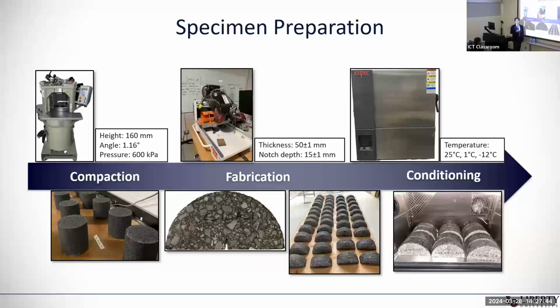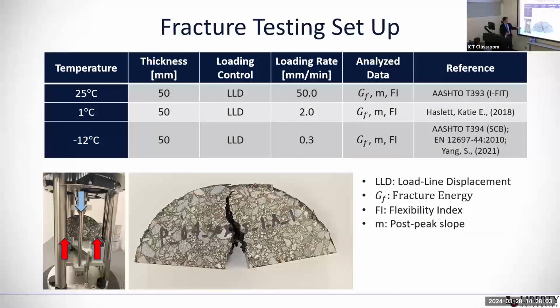So we compacted it to the 160 millimeter of the height to make the SCB samples, and then cut it into the half, and then put into the environment chamber to condition at 3 different temperatures, 25, 1, and minus 12 degrees Celsius. We ran the test in the AMPT machine that we have. For the 25 degree Celsius, we use a 50 millimeter thickness of the specimen with load line displacement control, and the loading rate that we use is 50 millimeter per minute according to the I-FIT specifications. And then we look at the fracture energy Gf and then flexibility index.